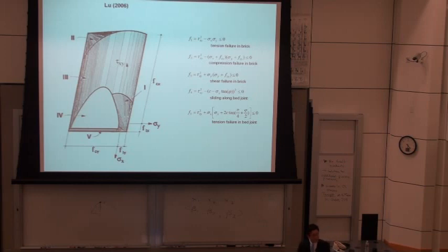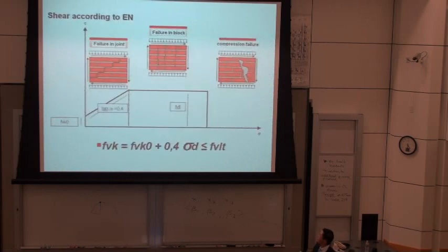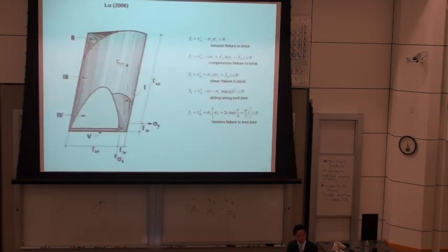Sliding along the bed joints is the same like before, a Mohr-Coulomb model actually, and tension failure in bed joint. And this is the model in the code, in Eurocode, which is just on Mohr-Coulomb, but also, as I said, based on Mann-Müller, where you have the initial shear strength, the tangens alpha, and also an f_vlt. So it says nothing else than that without any compression, you have an initial shear strength. Then the more compressive stress you have, the more shear strength you get.